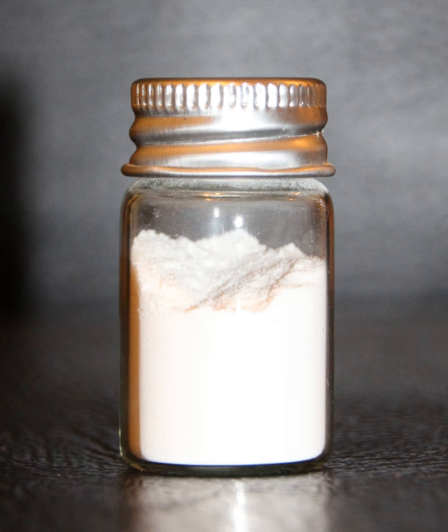Fumed silica. Fumed silica, also known as pyrogenic silica, is a very fine particulate or colloidal form of silicon dioxide. It is prepared by burning silicon chloride in an oxygen-rich hydrogen flame to produce a smoke of SiO2. SiCl4 + 2 H2 + O2 → SiO2 + 4 HCl.